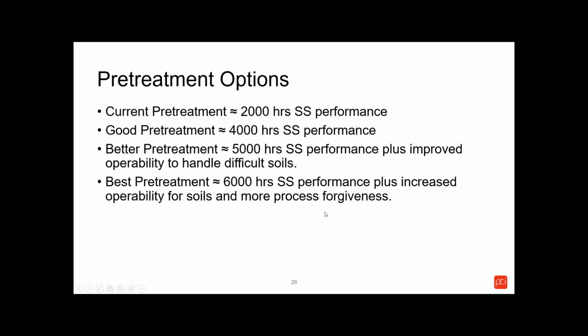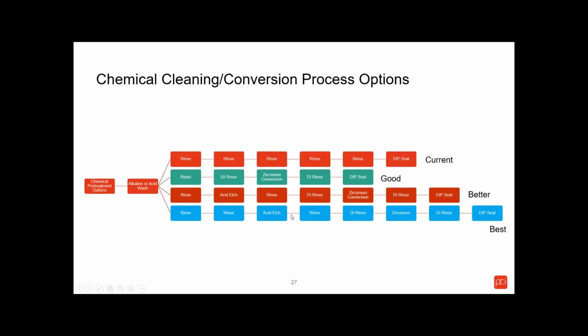So you basically end up with three pretreatment options before us. One is the current performance, about 2,000 hours. What we kind of call good pretreatment, which gets you to about 4,000 hours salt spray protection. A better, about 5,000 hours salt spray protection. That's where we did a little change, and we'll explain what that was. And then we went to the best pretreatment, which was 6,000 hours, using the method that was applied here. So here's how that worked out and how it applied.